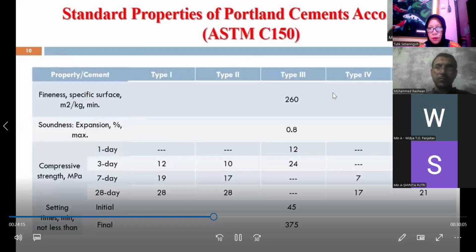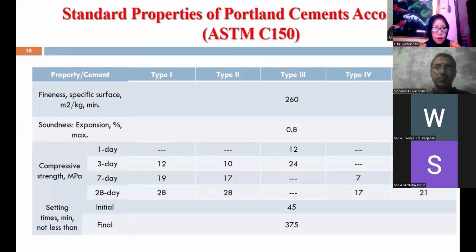For Portland cement, according to ASTM C150, the fineness by specific surface area for all types of cement must be a minimum of 260 square meters per kilogram. The soundness expansion of all these types of cement must not exceed 0.8%. Soundness or expansion is an indication of the soundness of cement. The other property is compressive strength by mortar cubes. The result of the compressive strength varies according to the composition of the type of cement, from 1 day to 28 days.